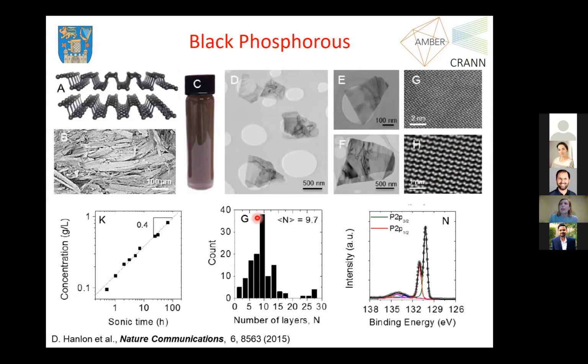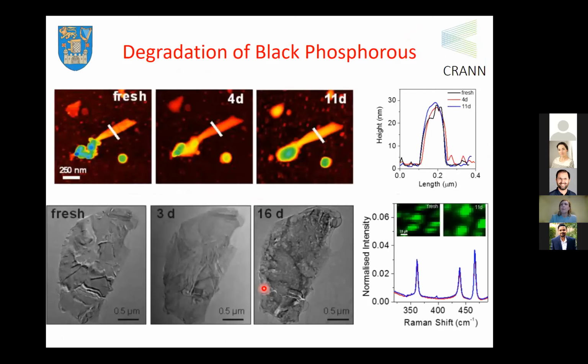We could get, as in any other liquid phase exfoliation methodology, a distribution of different thicknesses, mostly centered at about 8 to 10 layers with the standard exfoliation methodology. The interesting thing was that in some special solvents like NMP, N-methylpyrrolidone, and CHP, we found that the solvent had an added value. Not only was the solvent exfoliating the black phosphorus, but at the same time it was forming a protective layer that protected the exfoliated material from oxidation. For example, here there is a time series of the same black phosphorus flake, fresh as exfoliated, and then again after 3 days, and then 16 days.